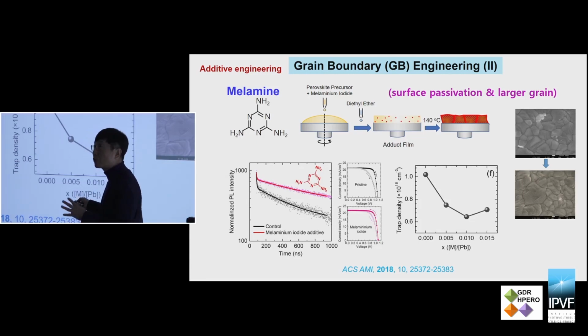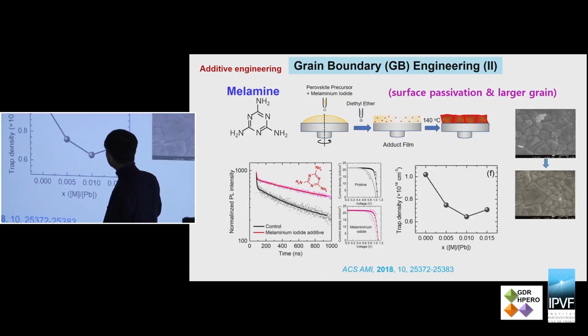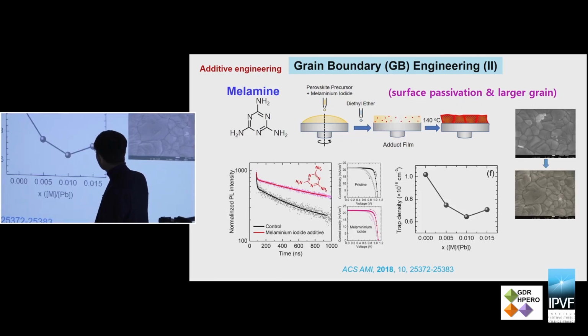And also for grain boundary engineering, you can add some kind of additive. This is one example. You can choose any kind of additive. Here we chose one by considering the functionality of the additive, and we used the melamine material, included it in the precursor solution, and then did some spin coating and heating of this spin coated film. And then this additive has a simultaneous effect of increasing grain size and also passivation of the grain boundary. So then you can see the trap density, which usually comes from the grain boundary, decreases by increasing the concentration of this additive.